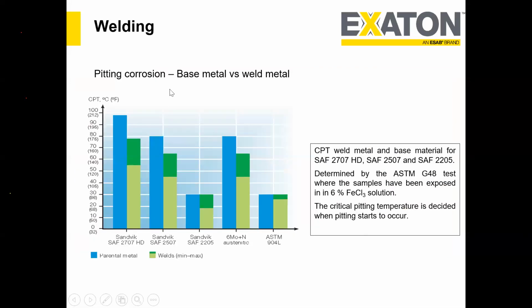Okay, so pitting corrosion in terms of welding, pitting corrosion of the base material versus weld metal, this is important, because the base material, the parent metal, always has a high CPT, as I explained, because they do the solution annealing operation. Whereas in terms of welding, it's basically an as-welded or cast structure, which has a lower pitting resistance. So for hyper duplex, we have around 55 minimum to 75 maximum. For super duplex, it is around 80 for the base material, but for the weld metal it is 42 to 60. Duplex is around 35.